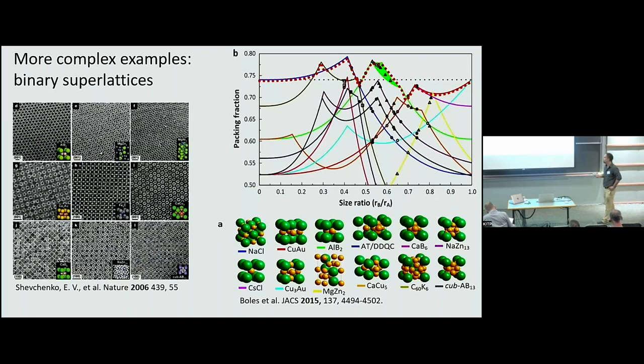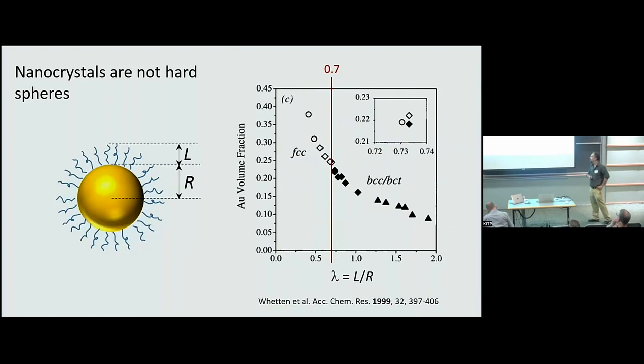Okay, so of course the conclusion here is that nanocrystals are not hard spheres, the ligands play a role. And there is this very nice paper that actually shows that you can have some universal behavior if you look at this softness parameter lambda, which is a ratio between the thickness of the ligand and the radius of the core. If you look at the structure as a function of lambda, then there is a threshold value of 0.7. Everything above that goes to BCC, and everything below that goes to FCC.